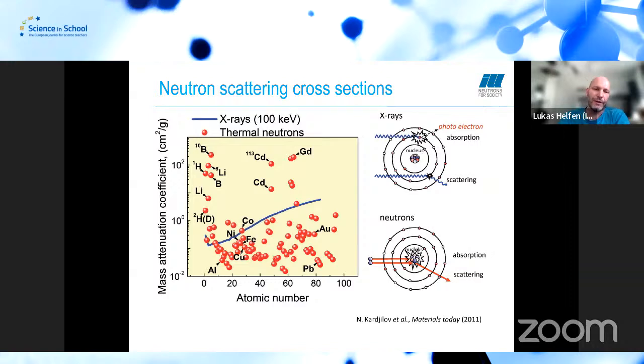Alessandro has already shown the chemical table of elements with the gray values showing the relative absorption. Here I show the relative absorption, or the mass attenuation coefficient comparison, between thermal neutrons and 100 keV X-rays. The X-rays, as Alessandro has already said, interact with the electron shell of the atom, while the neutrons interact with the nucleus. And what we see is a continuous dependence for the X-rays, but